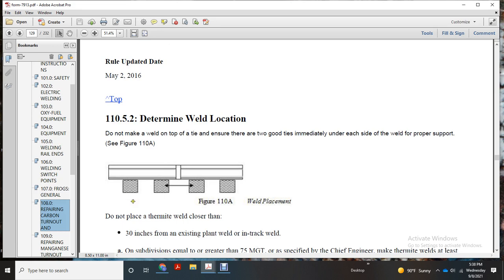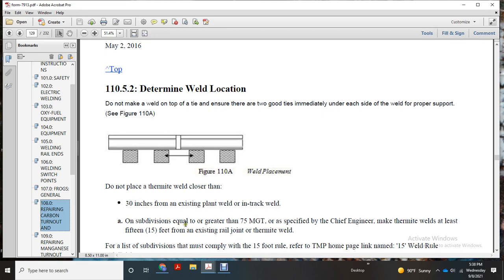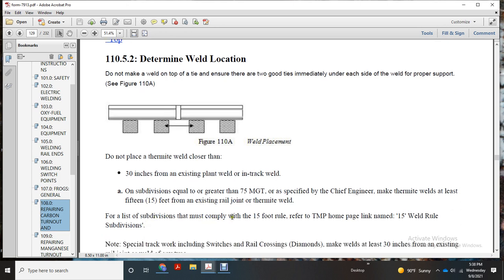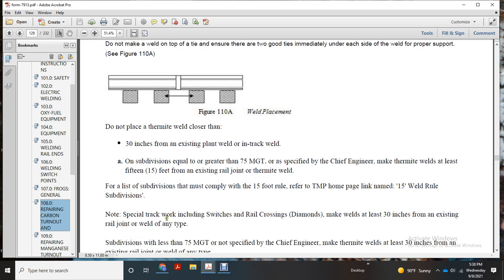Do not place a thermite weld closer than 30 inches to an existing weld or in-track weld, on a subdivision equal to or greater than 75 million gross tons, as specified by the chief engineer. Make thermite welds at least 15 feet from an existing rail joint. The thermite weld for the subdivision must comply with the 15-foot rule in the TMP on the homepage link. The 15-foot weld rule applies in special trackwork, including switches, rail crossings and diamonds.